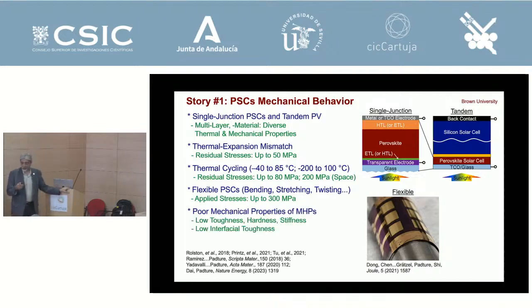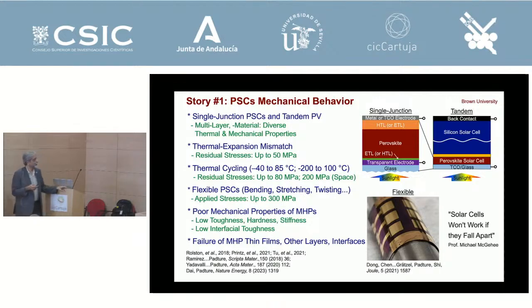And the problem is the stresses would be okay if the properties of these materials were good. But the properties of materials are really bad. I mean, the toughness is low, so they break if you look at them the wrong way, right? So you don't even need to apply stress. Their hardness is low, the stiffness is low, and the interfaces are very weak, and so they fall apart. So my ceramics friends laugh at me. They say, "Why are you working on this?" And I worked on structural ceramics, highest toughness composites, and so on. But the reason we are working on it is because they absorb light like crazy, right? Ordinary ceramics don't do that, right? These are very unique materials, and therefore we have to solve the other problems in order to take advantage of this, right?